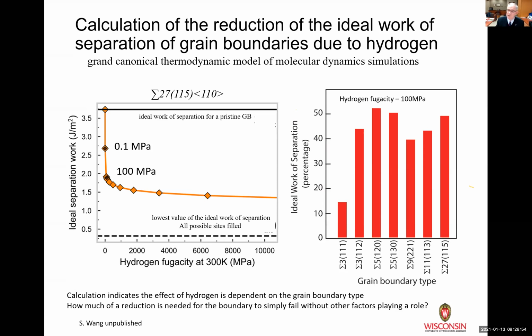The other thing that Shuai's work shows is that the amount of reduction that you get is grain boundary dependent, which I think is sort of obvious, but it's quite fascinating. So it says that even if you pump in X amount of hydrogen, and that would cause one boundary to fail, would that lead to system failure? Because all the other boundaries are strong and the crack won't propagate along the boundaries. So you need enough hydrogen on enough different types of boundaries in order to be able to get intergranular failure across the entire specimen.